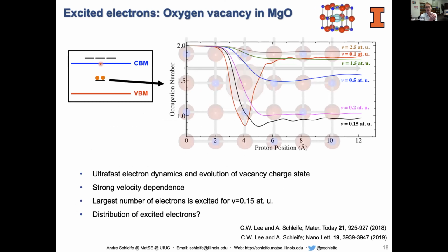But let me explain what happens in the material. So what we looked at is magnesium oxide. Okay, so you can see the bulk magnesium oxide cell here. It's also here in the background of this figure, you can see the atoms again. And we're looking at a situation where this material has an oxygen vacancy defect, right? This blue bubble here is actually the electron density, the partial electronic density associated with the defect state in this material. This is the same bubble essentially that you see here in the background of this figure.